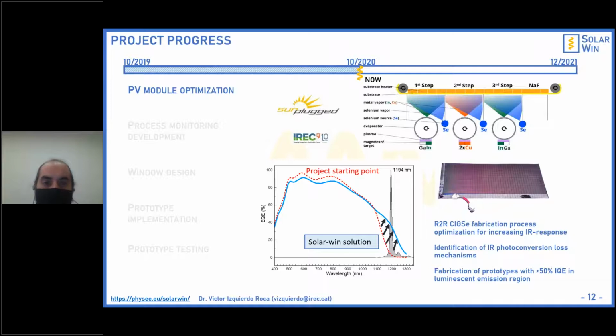Additionally, it is necessary to readapt the interconnection of the module to minimize the losses in the interconnection of the module. And for this we are working on the monolithic interconnection. This is a technology developed by Sun Plugged, but based on monoscribing process, and using interconnection of the cells based on conductive inks, and the printing of the conductive ink.